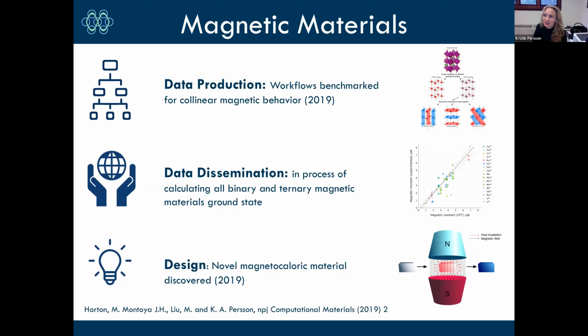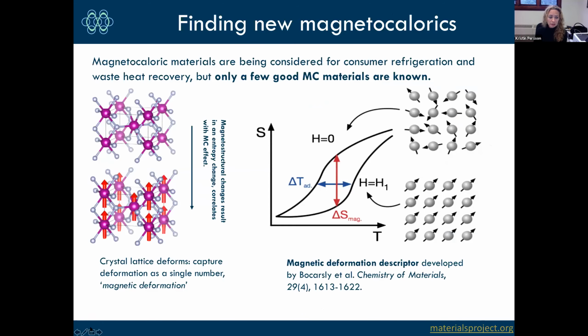So when you're going to design a material with magnetic properties, of course, you have to have a workflow that can robustly predict the accurate magnetic configuration of materials. So we started out with designing a workflow for collinear magnetic behavior, and that was published in 2019 and benchmarked against the best magnetic characterization data of oxides and other kinds of semiconducting materials that we could find. We're disseminating the data, and we are in the process of calculating all binary and ternary magnetic materials ground states, which is a large endeavor because you have to go through all the different iterations and at some point decide, okay, I think I found the lowest energy. And we also use this data to see if we can actually identify novel Magneto-Caloric materials.